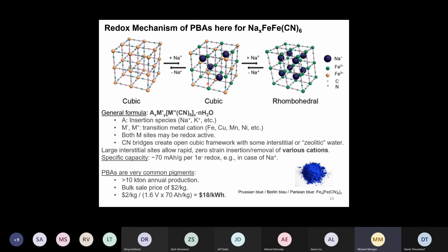And then we can even sodiate this material more, and upon this it would change its structure slightly to a rhombohedral structure, where these sodiums don't sit exactly on top of each other anymore. That might be better energetically. But you can see that now we have only these green dots, which is iron completely in the 2+ state.